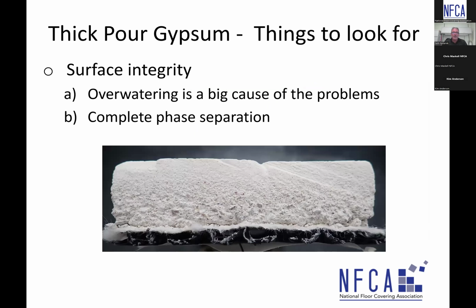To give you an idea of overwatering, this is an easy way to do a physical evaluation of any of these type products, whether it's a thick pour gypsum material, whether it's a self-leveling underlayment material, pick a manufacturer. But these liquid materials, and I say liquid because they're very flowable during placement, and then they chemically cure to develop strength. But the idea is having the right amount of water to make the material flowable, but not too much water to cause phase separation.